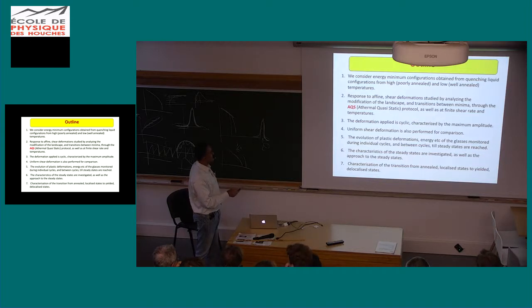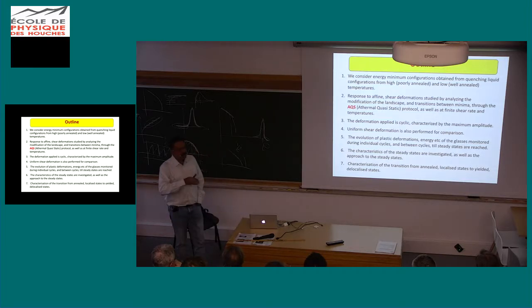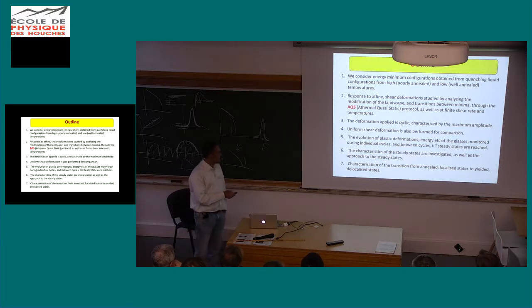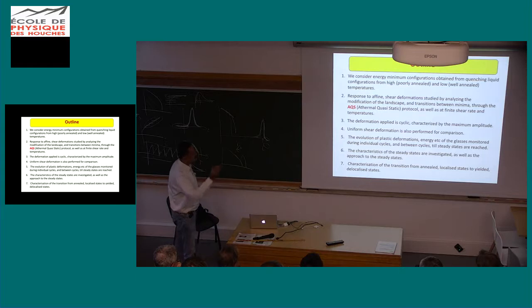So we look at the response to affine shear deformations through modifications of the energy landscape and transitions between minima through something called the Athermal quasi-static protocol. I'll describe it briefly. The deformation applied is cyclic, characterized by a maximum amplitude to which you deform the glass. We also look at uniform shear deformation and make a comparison. We study the evolution of plastic deformations, energy, etc. of the glasses through individual cycles of deformation, as well as the number of cycles is increased.